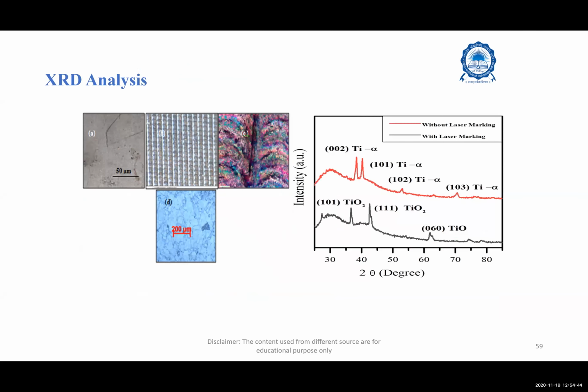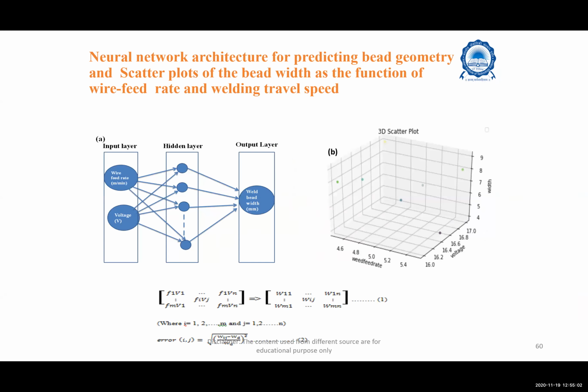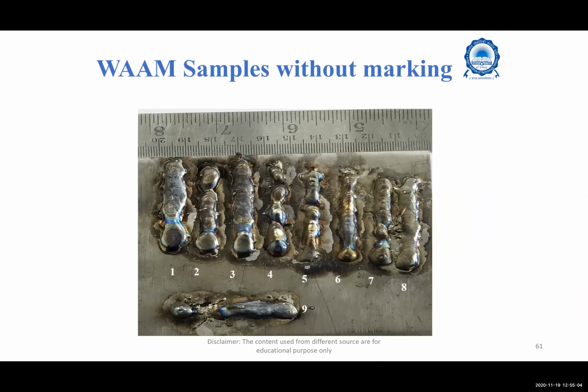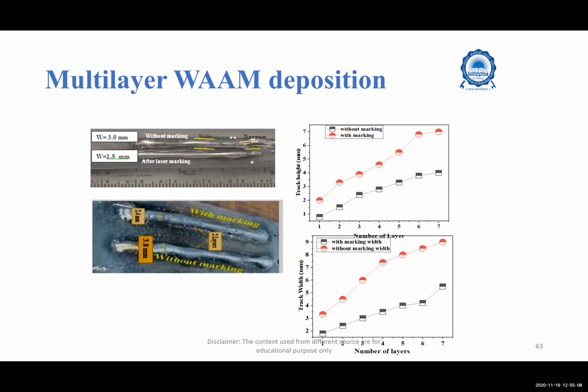This is an XRD analysis which we did, because since I am doing laser marking, there is a chance that by employing such laser marking, I can tune the crystal structure. That is one major aspect which we have attempted over here. So we went for a complete theoretical analysis. This is a WAAM sample without marking, and this is with marking. This gives you better clarity on how the surfaces were made.